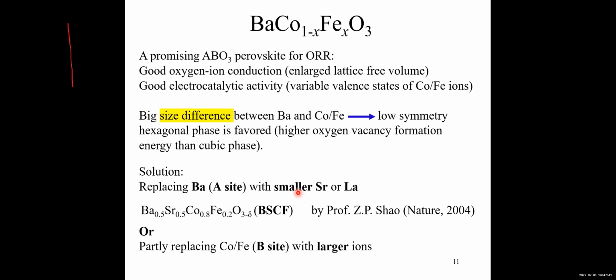And this hexagonal phase will increase the oxygen vacancy formation energy, which is not very good for oxygen ion conduction. So the solution is either to dope the A site with some smaller elements, such as the BSCF material developed by Professor Zhongping Shao, or replace the B site with some larger ions, so that we can reduce the size difference between A site and B site.